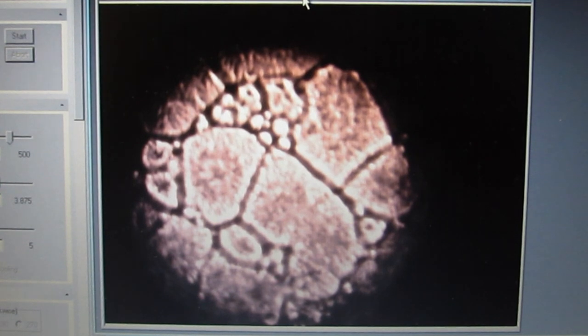If we look at it under the microscope, we are able to achieve up to millimeter-scale large crystal grains. Normally for a crystal to grow it usually requires high temperature or sophisticated processing, but this method is a low-temperature and easy solution processing approach.